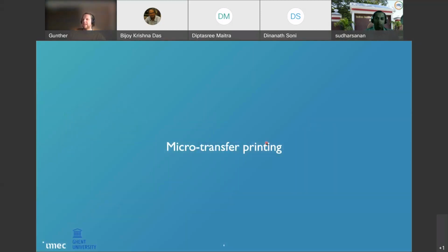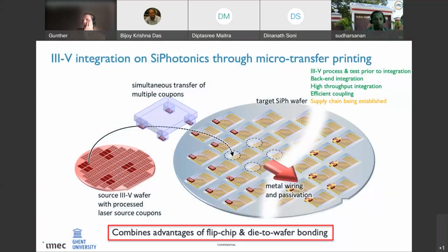So let me first explain to you what microtransfer printing is. I'll do this by this cartoon, where on the left-hand side you see our III-V source wafer. On that III-V source wafer, we have already processed the III-V optoelectronic components that we want to integrate on the silicon photonics target wafer. So that means that after processing of the III-V, we can actually test these components and basically select the known good dies from this wafer. So that's what it has in common with flip chip integration, is that you can fabricate the III-V devices on a III-V source wafer and test them up front. So you have this known good die concept.